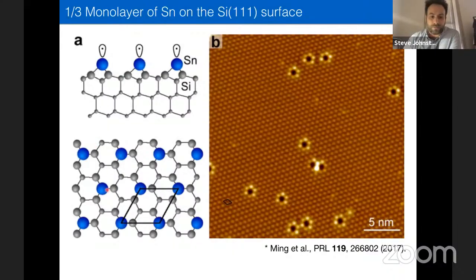The atoms will arrange themselves in these really nice triangular lattice structures that are separated by several lattice constants on the silicon surface. And so what happens is that the silicon 1,1,1 surface has these dangling bonds that it wants to passivate. And so the sp bonds of the atoms will bind to the surface. They'll create a covalent bond with the surface and leave sort of one half-filled dangling bond pointing perpendicular to the surface. In the case of tin, what happens is you get one electron per orbital.